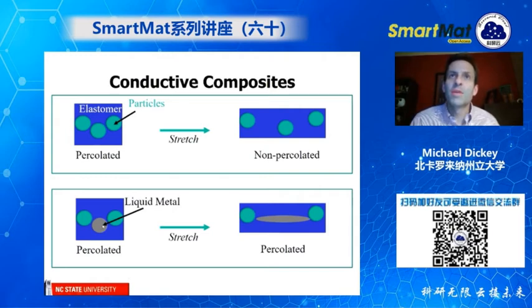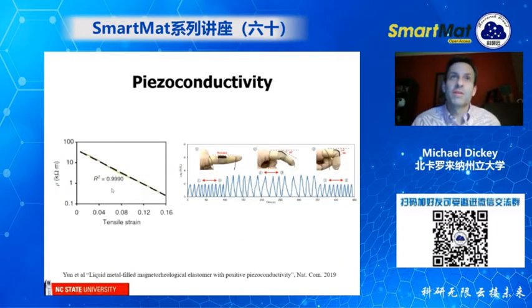And in our case, we have liquid metal along with these solid fillers. When you stretch it, you actually decrease the gap between the fillers and it becomes more conductive. Not only does it become more conductive, but it becomes much more conductive. So this is the resistivity plotted as a function of tensile strain. And you see this is quite a small strain, and the resistivity drops by 3 orders of magnitude. So this is really great for sensing. In fact, if you put this material on a finger and you measure the change in resistance, you can see that when you bend the finger, the resistance goes up, and then you let it go.